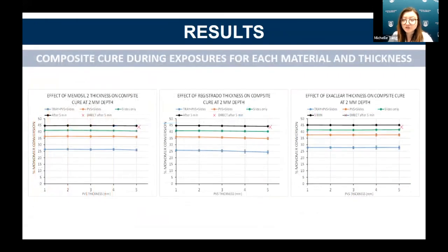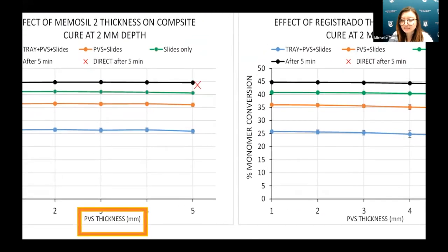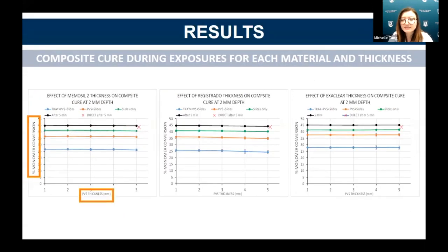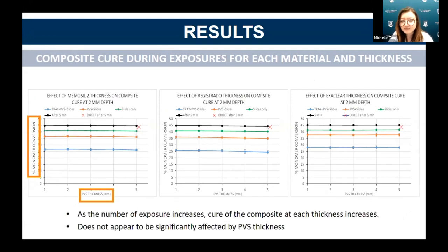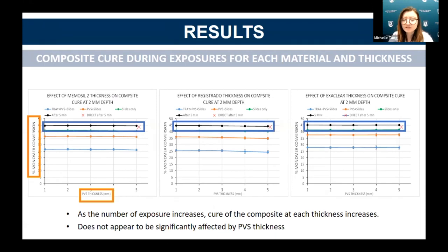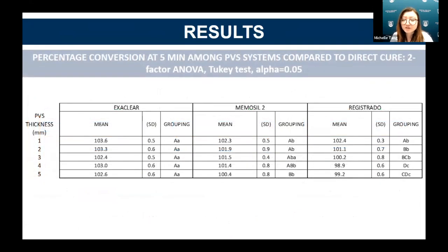For each PVS material and exposure, the effect of PVS thickness on the x-axis against percent monomer conversion on the y-axis was plotted. As can be seen, as the number of exposures increases, the cure of the composite at each thickness increases. However, as we move along the x-axis for each material, there does not seem to be any significant effect of the PVS thickness on monomer conversion. In fact, the percent cure detected after 5 minutes at each PVS thickness was slightly greater than the direct exposure control group curing. A 2-factor ANOVA and Tukey test was conducted at an alpha of 0.05.